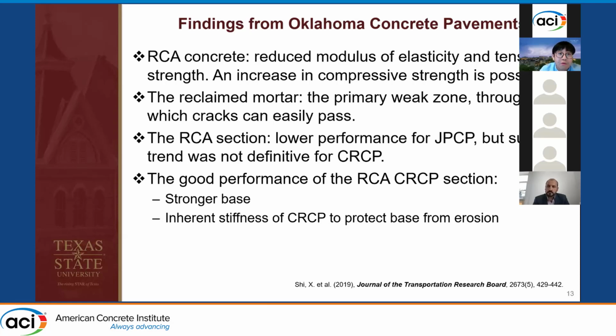For the RCA concrete, we had a reduced modulus of elasticity and tensile strength, but we did find an increase in compressive strength on I-40. And for the reclaimed mortar, we found it is a primary weak zone and the crack can easily pass through. And for the field studies, we found the JPCP section, RCA section had a lower performance, but for the CRCP, the performance was similar to the control.